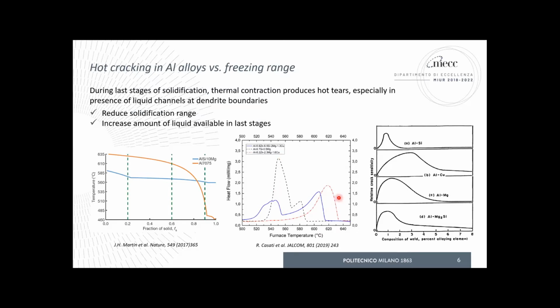on to the plot in the middle of this slide, we have a good example, I guess, at least. Again, there is a comparison among similar alloys as those on the left side. The red line, these are DSC scans, so differential scanning calorimetry tests. The red line shows the solidification curve for a quite similar alloy. It was a 7000 series alloy. It shows that there is a very wide peak corresponding to the solidification and a small tail right here, okay? More or less, all the solidification process develops over a quite large temperature interval, more or less the same information we got from this diagram here.